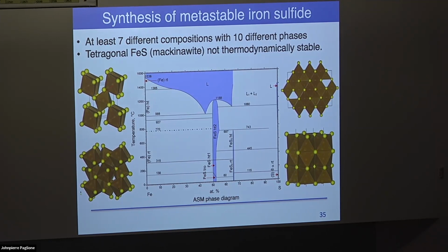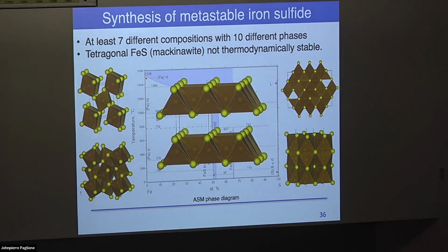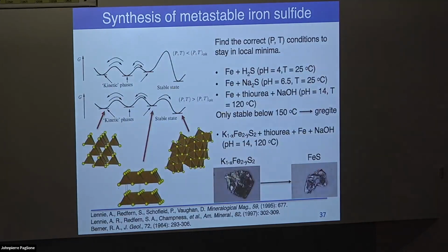So if you wanted to make it, you might have to start thinking about it being a metastable state and actually using kinetics. So this is the layered analog to iron selenide. We wanted to see if there was a way to make this, to see if it is a superconductor as well. Basically, we can do exactly that. We can find the correct pressure and temperature conditions to actually stay stuck in one of these local minima and form this layered iron sulfide.